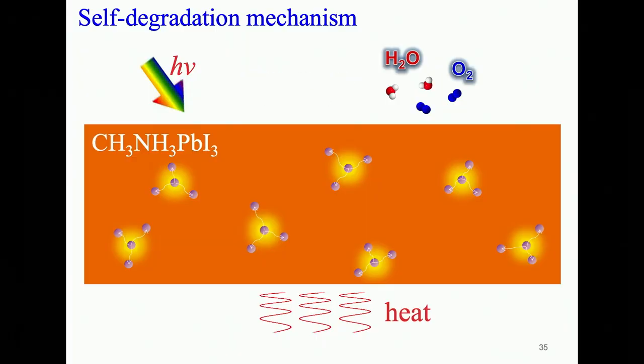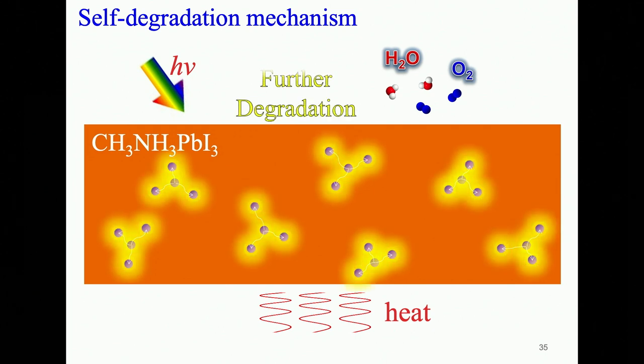Iodine-2 is quite diffusive and can migrate to other regions of the perovskite layer, leading to the further degradation of the perovskite. As a result, more iodine-2 is generated, and so on and so forth. Such degradation events will finally lead to the degradation of the perovskite layer at a much larger scale. And eventually, the performance of these perovskite solar cells will deteriorate.